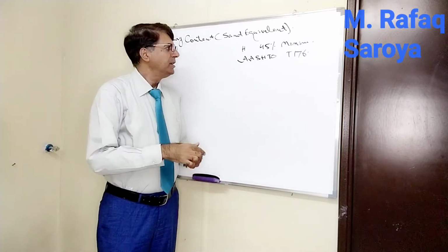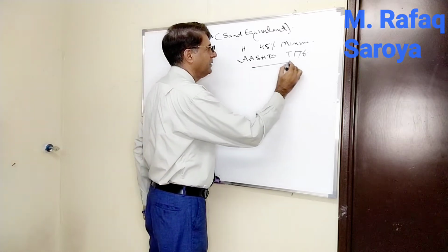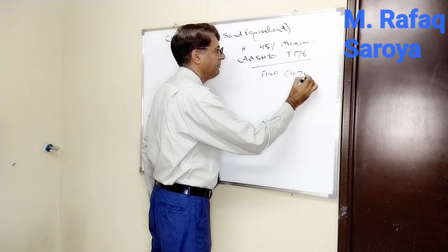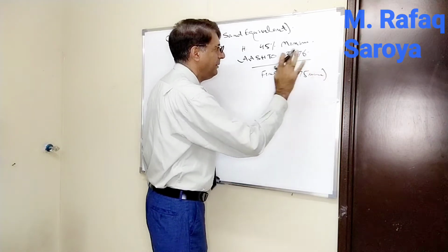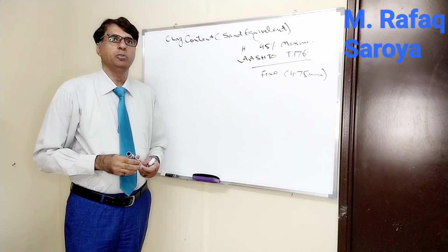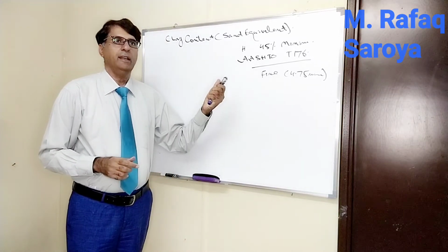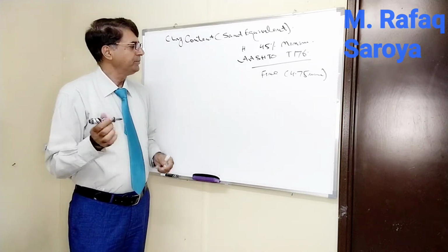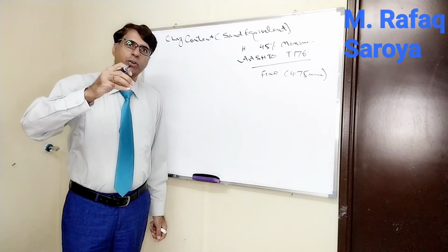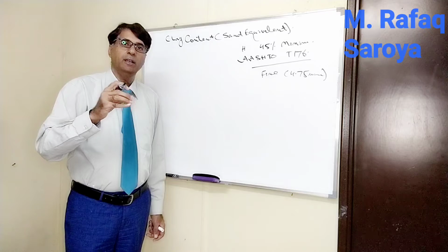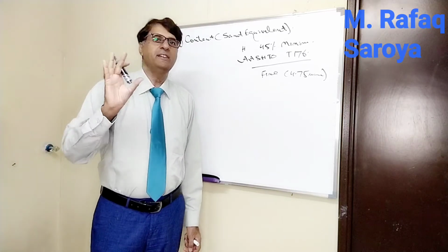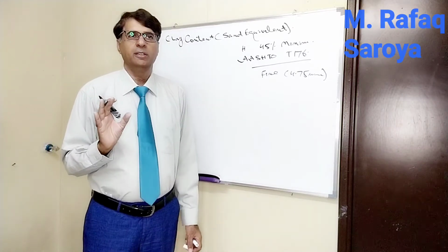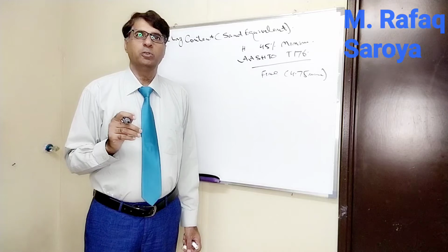Fine aggregates are used for this one, passing 4.75 mm. This type of aggregate is used in order to check our clay content under the sand equivalent value. Now, how we will do it? We are going to force the clay material to remain suspended in a graduated cylinder by putting in a calcium chloride solution.